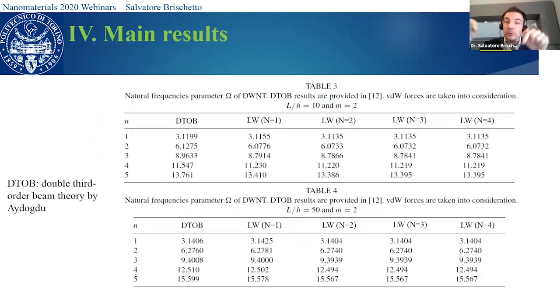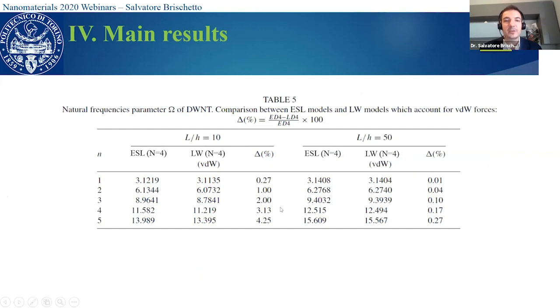Another possibility is to include the layer-wise approach. So in this case, we have the van der Waals forces, okay? And the results are completely different with respect to the equivalent single-layer approach. In this case, we can see the difference between the equivalent single-layer approach and the layer-wise approach with the van der Waals interactions. So the differences increase when the order of frequencies increases, and it is bigger for the short carbon nanotubes.